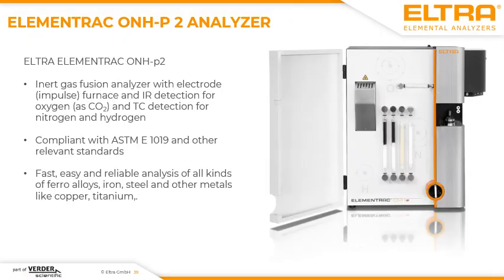For ONH analysis, ELTRA is utilizing the Elementrac ONH-p2. It's an inert gas fusion analyzer with an electrode furnace, and it measures the elemental oxygen, nitrogen, and hydrogen. Hydrogen and nitrogen are measured in a thermal conductivity cell, whereas oxygen is measured as CO2 in infrared cells. This kind of analyzer is compliant to more or less every international standard, which we discussed before, for example, ASTM E1019.